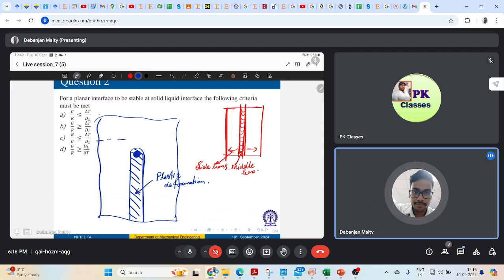Let's say I am taking a section AA, which is ahead of your heat source. My heat source is starting from this blue region. Now, will there be any effect on section AA on the stress that will be generated if it is ahead of your heat source? Of course, that will not significantly be affected by the heat input, right? So, due to temperature change during welding, my residual stress will be essentially zero at section AA.